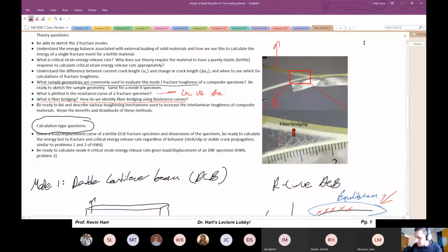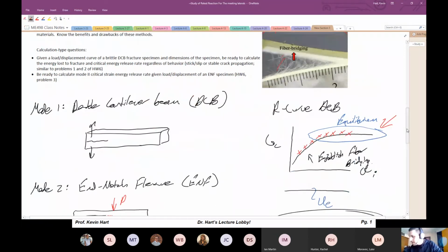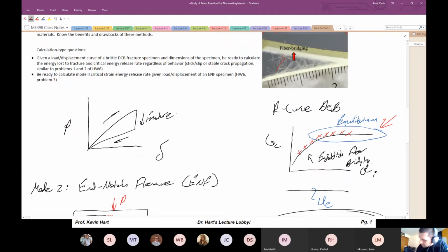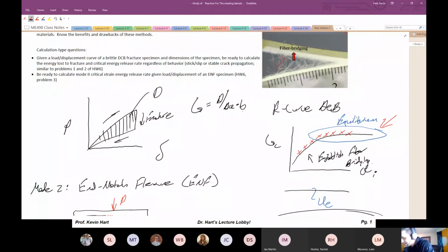Calculation type questions. Given a load displacement curve of a brittle DCB fracture specimen and dimensions of the specimen, be ready to calculate energy loss to fracture. I sketched that out before. The idea is that if you have some load and displacement curve of some fracture specimen, let's call it a DCB specimen, here's delta, here's load. You load this up, there's a fracture event, and you unload. Be ready to calculate the area associated with a fracture. So here's D. Then if you have sample dimensions, G is just D divided by delta a, the crack advance, multiplied by the width of the sample b. That would be a sample calculation you could do on the test. It's areas under the curves. That's all it is in this class, I guess.